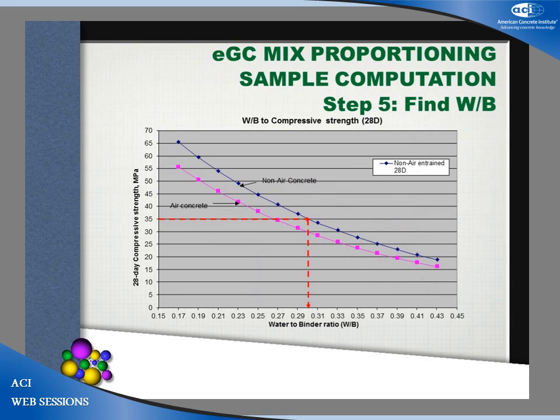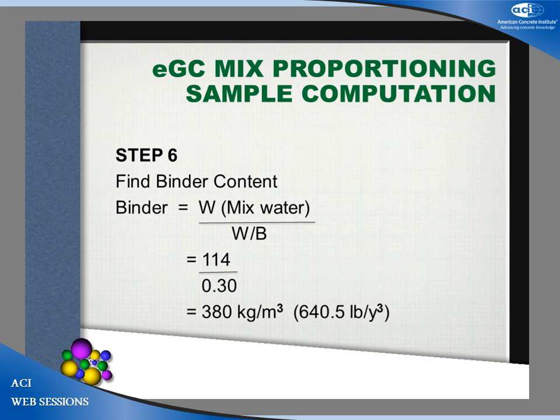So step number 5, find the water binder ratio. In our chart, our concrete is non-air-entrained concrete, the blue line. Our targeted required compressive strength is 35 MPa, so the water binder ratio would be 0.30. Step number 6, the binder content or cement content, whatever you call it: mixing water divided by water binder ratio. 114 we got from step number 4, 0.30 we got from step number 5. So that gives you 380 kg per cubic meter, that is 640.5 pound per cubic yard.